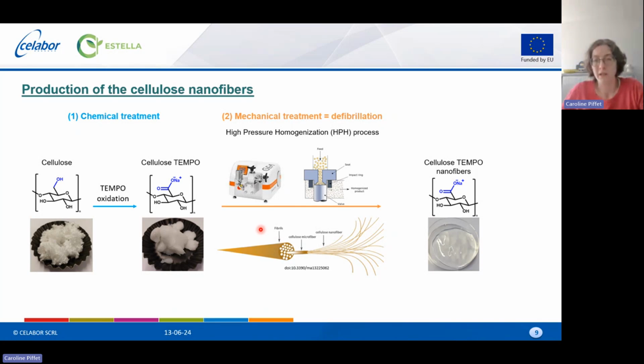And the technique we used for the mechanical treatment is high pressure homogenization. So this is this kind of machine, and the cellulose is put in water. Then this mixture goes through a very, very thin hole, and because of shearing, this causes the separation of the nanofibers. This technique was chosen in the ESTELLA project because it is upscalable, and we would like to have a production as industrializable as possible. And thanks to this technique, we obtained the cellulose nanofibers functionalized with the carboxylate groups. This is, as we already saw, a jelly aqueous dispersion at low concentration, about 1%.